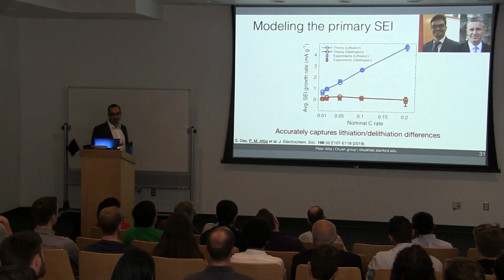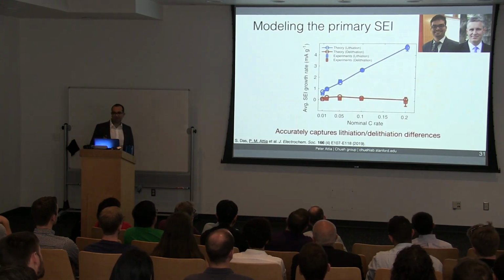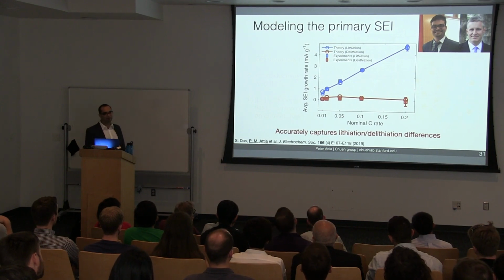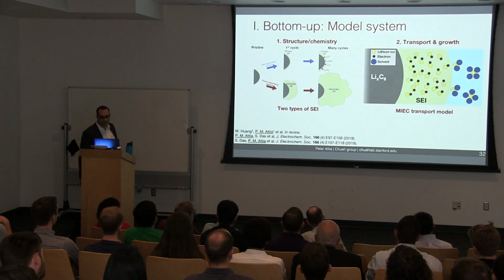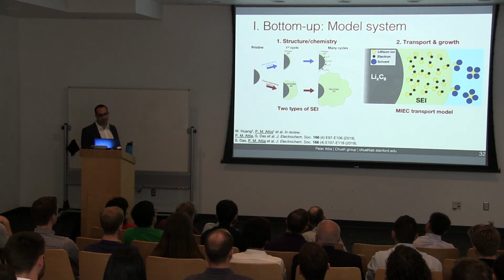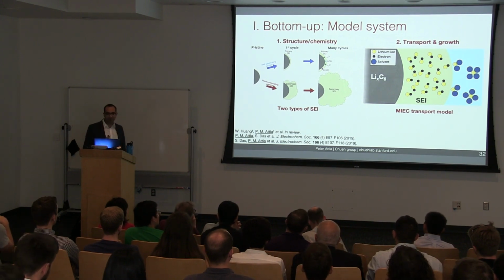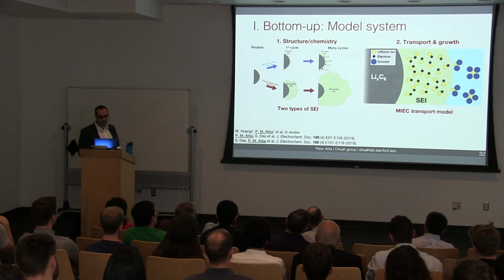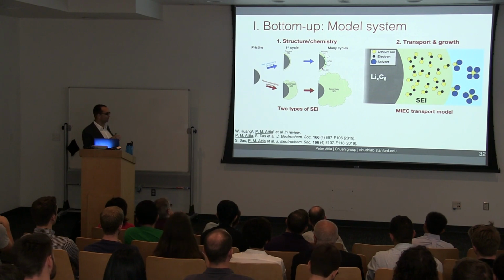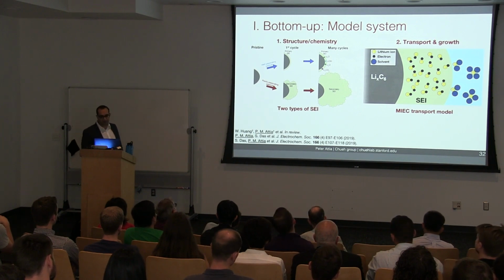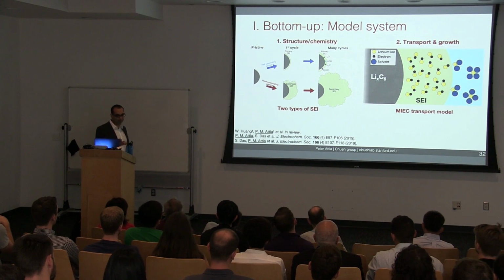We then developed simulations to better understand this highly complex system. We found that this type of model can accurately capture the unexpected directional dependence of SEI growth. So in this section, we first characterized the structure and chemistry of the SEI using Cryo-EM. We saw both thin primary SEI and thick secondary SEI. Second, we used electrochemistry to measure the kinetics of electrochemical SEI growth. We found this really surprising result that the SEI grows much faster during lithiation than delithiation. And lastly, we put this all into a model, which is able to explain the directional dependence. Hopefully, these insights can be used to design new electrolytes that form good SEIs.